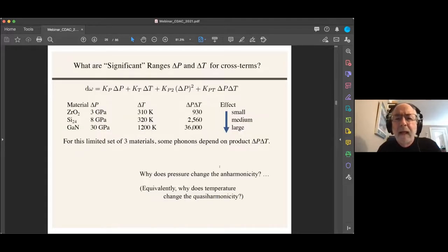So let me get back to that question on what's important for the ranges of pressure and temperature. We went through this before, and we've done a little bit of work with Tim Strobel at Carnegie on Raman spectroscopy, where we selected a few modes for zirconia and silicon. And Jane Harriman did some calculations on gallium nitride, where she could go to much higher pressures and temperatures. And we could see little things that maybe we could see in neutrons here for the zirconia. This is a medium size effect. We could definitely see it.